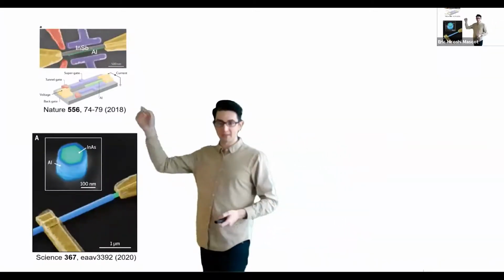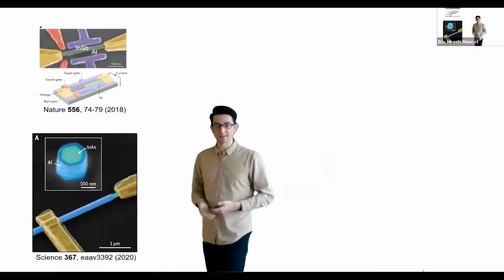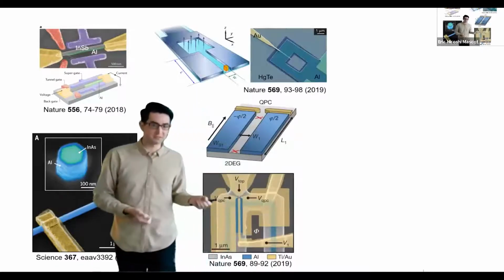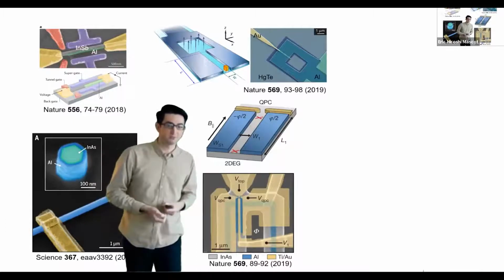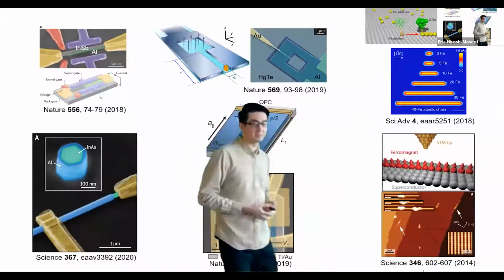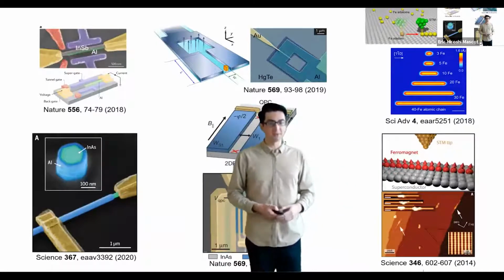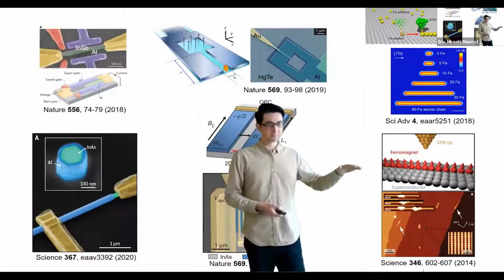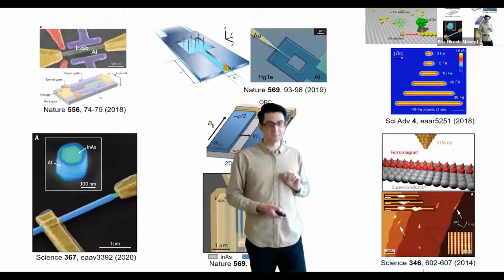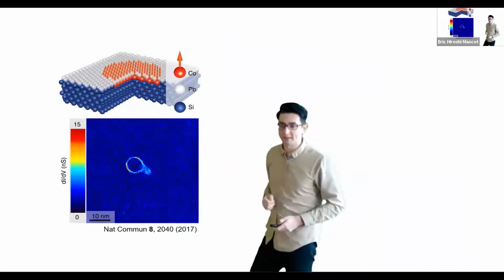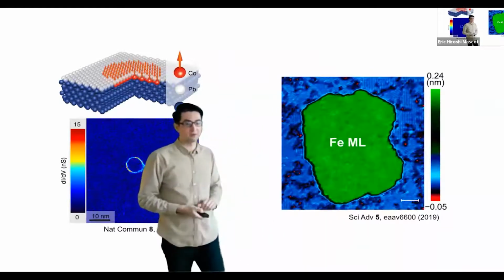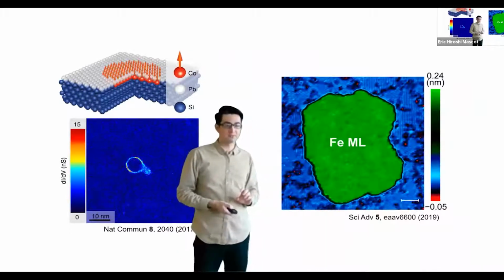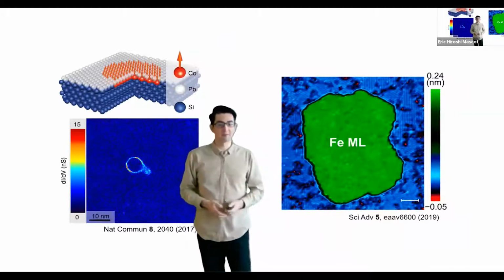There's been many different ways to try and realize these Majorana zero modes. One example is using semiconducting nanowires and then encasing that in a superconductor. Another is to use Josephson junctions and putting that on the surface of a semiconducting thin film. And what I'll be talking about today are these magnet-superconductor hybrid systems, where you have a superconducting substrate and magnetic atoms on the surface. And there's also 2D realizations. Here we have magnetic cobalt atoms and superconducting lead. And also this example where we have iron monolayer grown on top of the surface of rhenium. And this example I will talk about later in my defense.